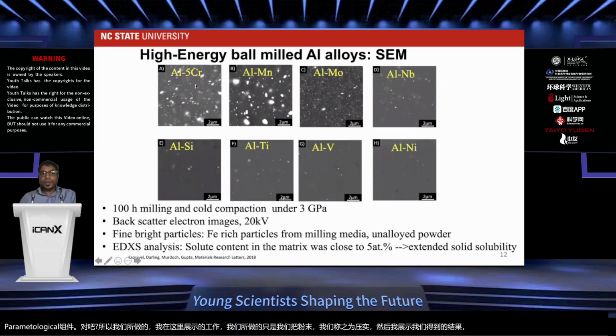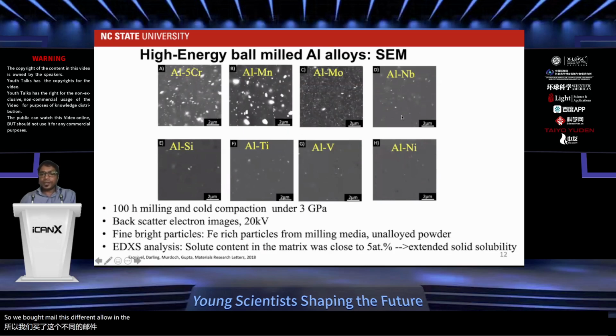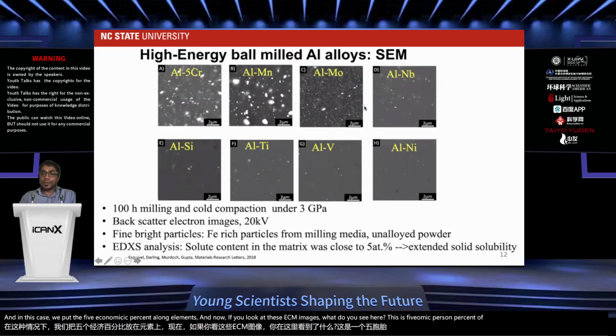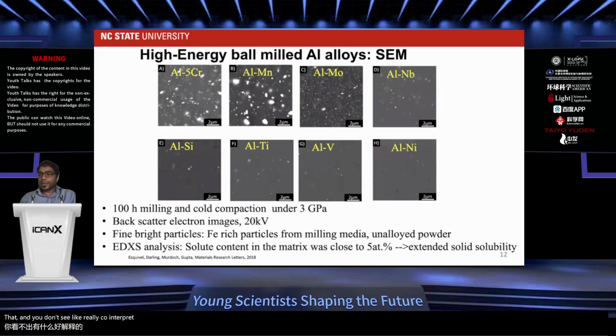We ball milled these different alloys. In the beginning, we selected 8 alloys: aluminum chromium, aluminum manganese, moly, niobium, silicon, titanium, vanadium, and nickel. In each case, we put in 5 atomic percent alloying elements. Now if you look at these SEM images, this is 5 atomic percent of the alloying elements, so quite a lot of that. And you don't see really coarse intermetallics. This is a 2 micron scale bar, right? You see most of them are uniformly distributed.